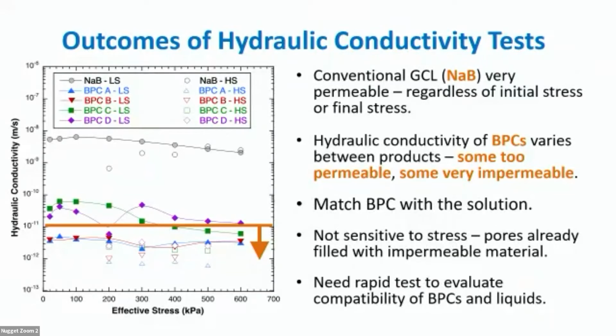What did we find? First of all, we did tests with a conventional GCL and with a bentonite polymer composite, 4 of these bentonite polymer composite GCLs. The first thing that we found was with the conventional GCLs that they were very permeable. The solution is just too strong for conventional bentonite. So a conventional GCL that you could buy from a manufacturer is not going to function in this application.